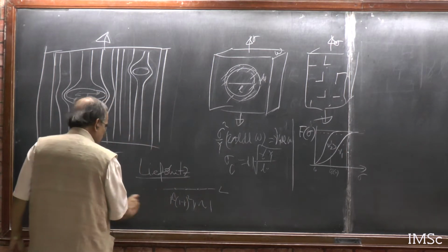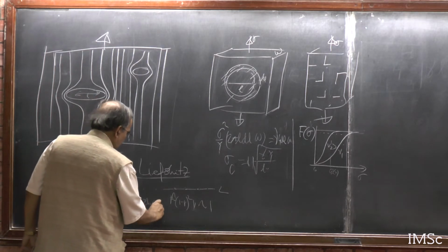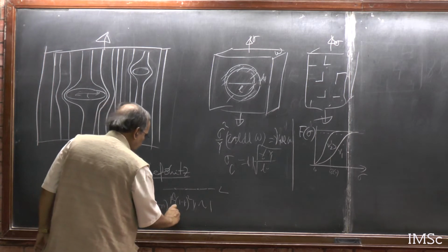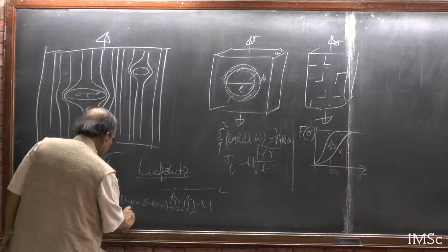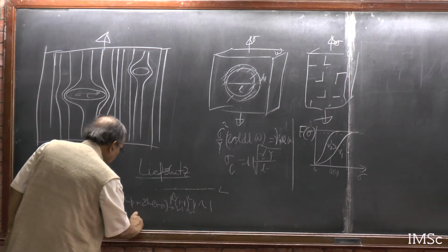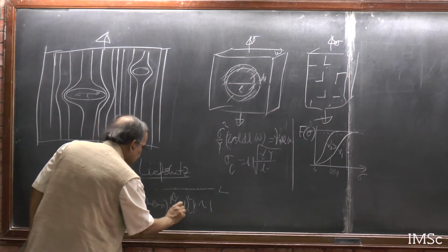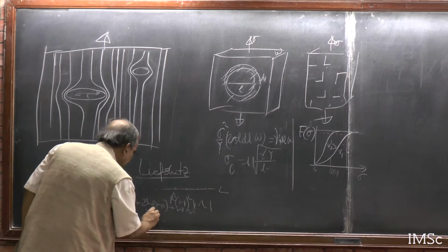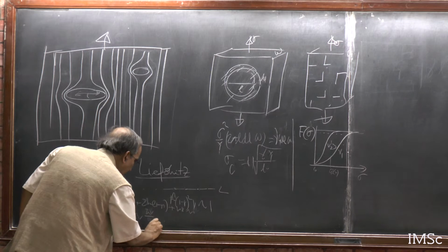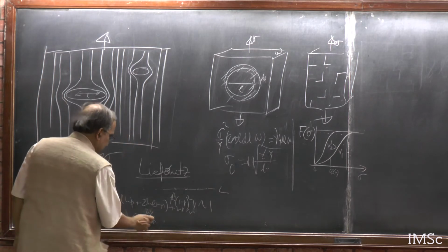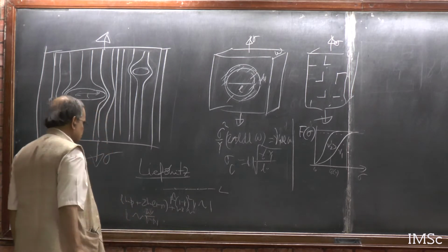And then that means if you take log, L log P plus some 2 log of 1 minus P plus log V will go to 0, and that means L will go as log V divided by minus log P. Since P is less than 1, log P is negative, so you just have this.